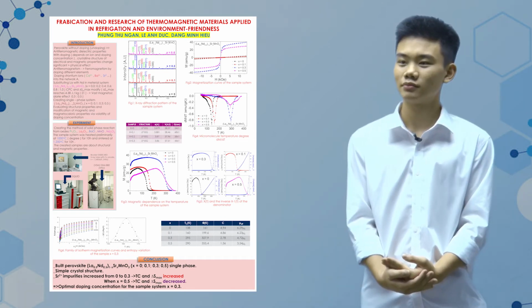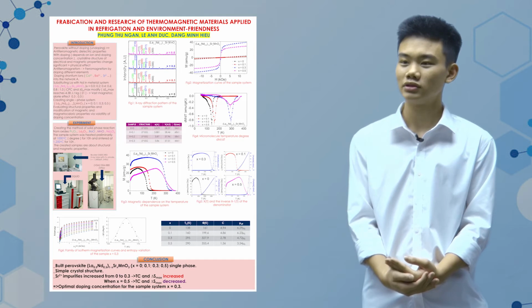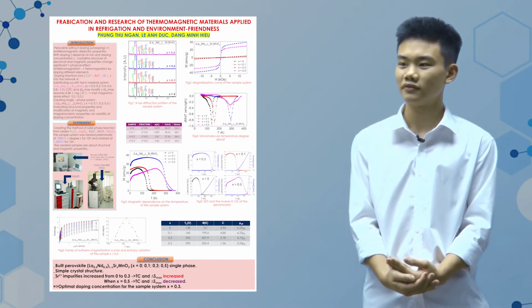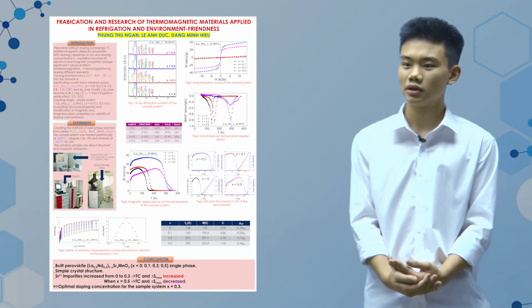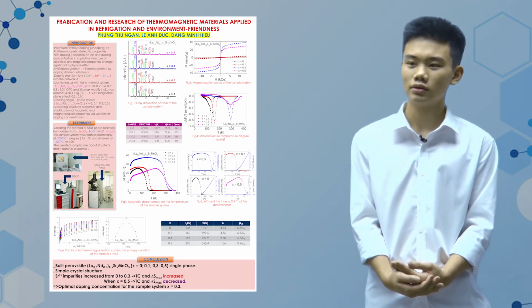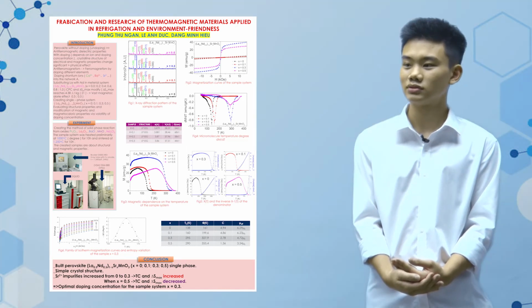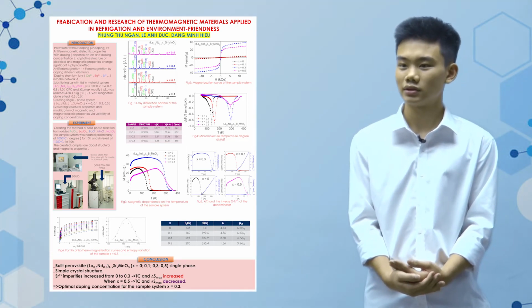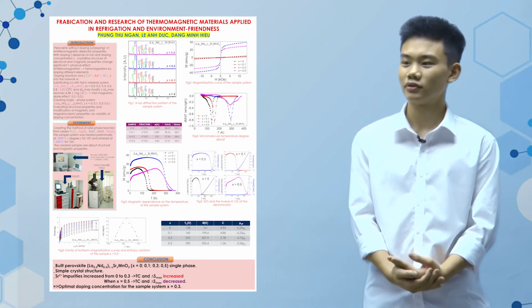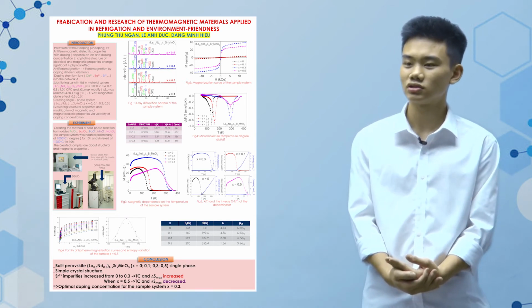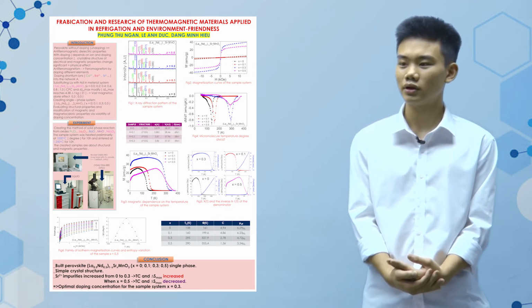Now we briefly talk about the experiment. The samples La0.5Nd0.5(1-x)SrxMnO3 were fabricated by a solid phase reaction of the oxides La2O3, Nd2O3, SrO, and MnO. The samples are preheated at 1000 degrees C for 10 hours and annealed at 1250 degrees C for 10 hours. The samples after manufacturing are measured for crystalline structure and magnetocaloric property.